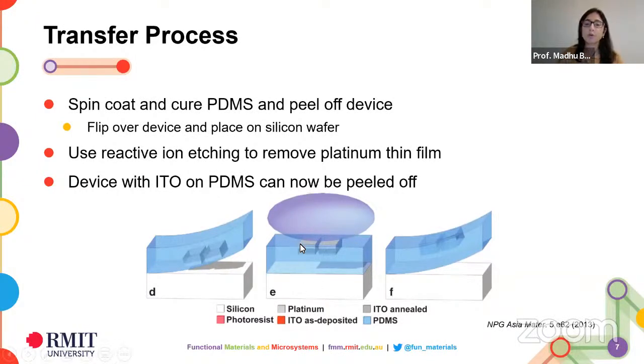So when you flip it over, what you're left with is platinum on top, the indium tin oxide semi-embedded in the PDMS and a little bit sitting on top, and the PDMS as a substrate. Now you can then use a dry etching step, get rid of your platinum, and at the end of it, what you're left with is your indium tin oxide devices sitting on your silicone rubber or your polymeric substrate.